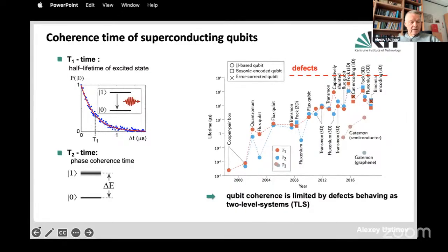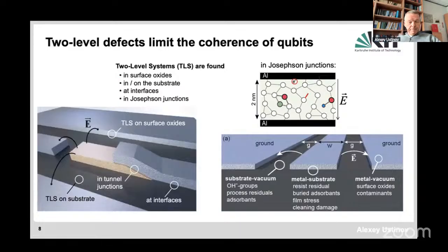We would like to study actually the physical properties of those defects and actually understand what they are. So the defects are of unknown origin. What we know about those defects is that they occur in disordered materials. They can occur on the tunnel barrier of a Josephson junction, which will be basically inside the superconducting qubit. They can also occur on the surfaces of superconducting electrodes, which when the circuit is fabricated, are in contact with air, and they get oxidized, of course. And then there could be oxides, some disordered fractions of the materials, could be adsorbates on the surface. This could be residuals of the photoresist. And they can be also defects in the junction.